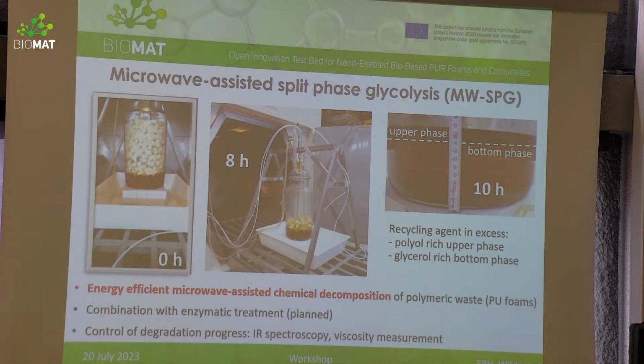Now I would like to switch over to the setup of the pilot line, the microwave-assisted split-phase glycolysis. So we start basically here with a reactor which is filled with, below we see in brown, the liquid phase of the recycling agent. This is glycerol in this case. Glycerol has been chosen because it is a byproduct of oil refining processes, and people are really interested in getting rid of this glycerol, so it could be used in a sensible way if it could act as recycling agent in the case of the decomposition of polyurethane foams.